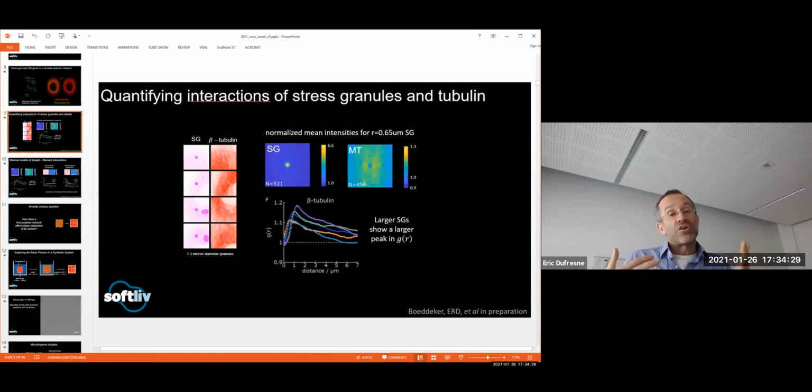My answer is that if you can grow those droplets to the point where they're all the same size faster than the characteristic time scale at which these bonds are being broken and made, then I think you could still make a uniform emulsion. But certainly if the growth process is slow compared to the time scale of those bonds being broken and remade, then I completely agree with you that all of the physics I described today would completely go away.